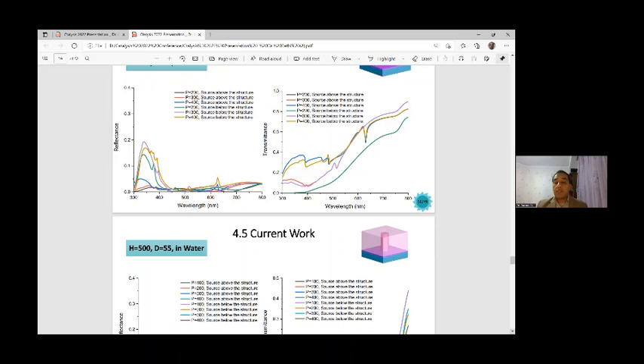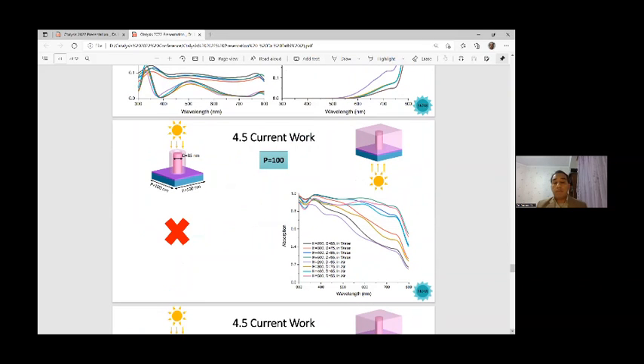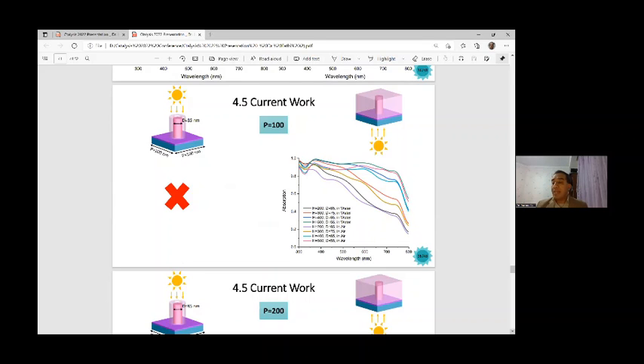Also, from slide 38 to 41, these three slides, P is the center to center distance, the distance between the center of a cell and the center of adjacent cells in the periodic total structure. Structure 2 cannot be fabricated and implemented, because if we put the cells together in the total periodic structure, the perovskite will overlap from one cell to other cells. So for P equal to 100 nanometers, this structure 2 is not feasible to fabricate and implement.